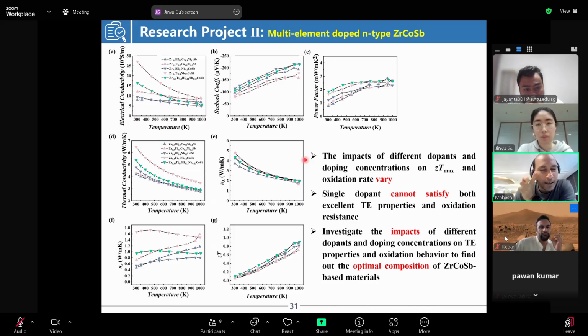How do you tune the carrier concentration? These Heusler alloys, right? Mostly are N type. Tuning the carrier concentration is by the number of valency, the number of electrons. So when you change the nickel or cobalt to nickel, the number of valence electrons increases, right? If you increase the nickel content, cobalt, nickel, copper, zinc, yeah. This is different from our oxide materials. Do you know the difference between Heusler alloys and oxide materials in tuning the carrier concentration?